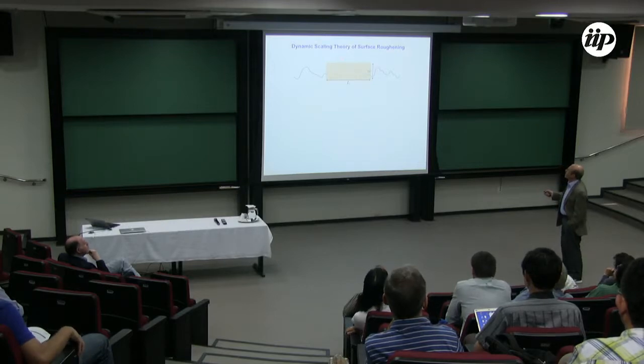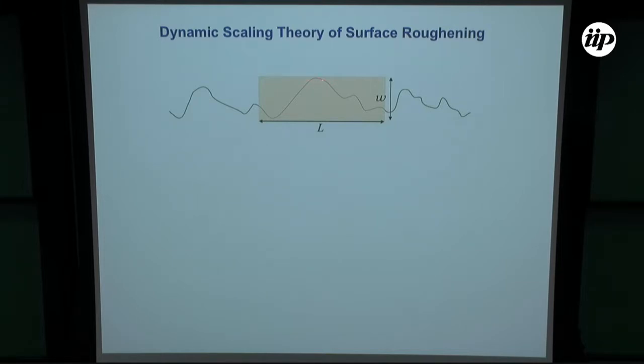As we said, surface roughness depends on this length as well. If this L was very small, here you would have very little roughness. But if the length is large, you see the roughness is this much from the peak to the bottom. So this is as relevant as the vertical distance W. This is the horizontal distance L. Well, the thing we can do is to say that perhaps from a statistical mechanics point of view, from a physics point of view, this width represents some kind of correlations that exist between different parts of this evolving surface. You have a surface that's evolving, and the way this roughness is generated is through the correlations between the different parts of this surface in this direction of the growth, vertical growth.